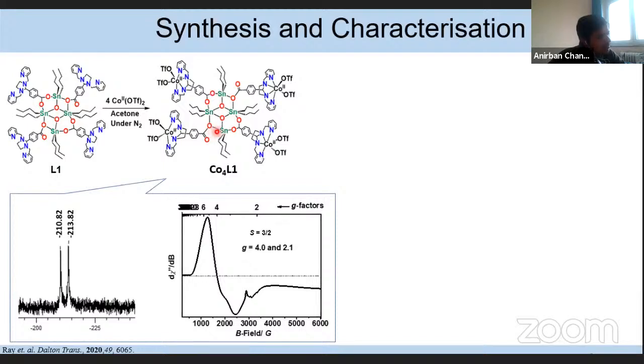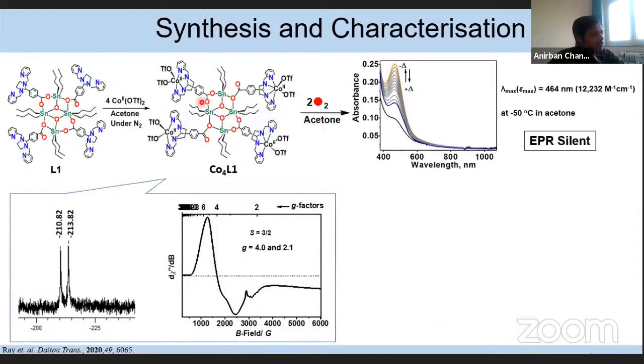And then I did the oxygenation of this tetranuclear cobalt(II) complex, and upon oxygenation I found that a UV-vis absorption band starts forming with absorption maximum at 464 nanometer, and a molar extinction coefficient value around 12,000 at minus 50 degrees in acetone. The newly formed species is reversible and depends on temperature. So with increasing temperature, the yield decreases, while with decreasing temperature, the absorption spectra always increase. That means the species that is forming is also increasing in yield.